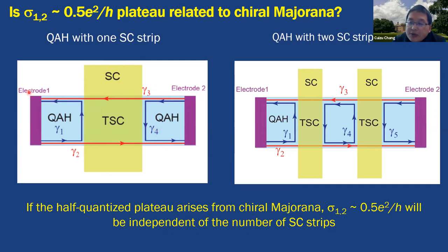And if we take the two-terminal measurement, we could check if there is chiral Majorana physics. But in order to check from this two-terminal measurement whether the e squared over 2h is related to chiral Majorana or not, we can put two superconductor strips. This is very simple in our experiment. So if you put two superconducting strips, in principle it forms five chiral Majoranas. And from gamma one to gamma four, when you take the two-terminal measurement, if the two-terminal resistance e squared over 2h is indeed related to the chiral Majorana, it should always be e squared over 2h.